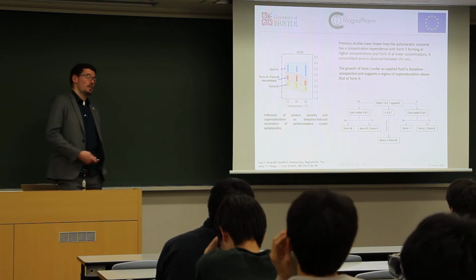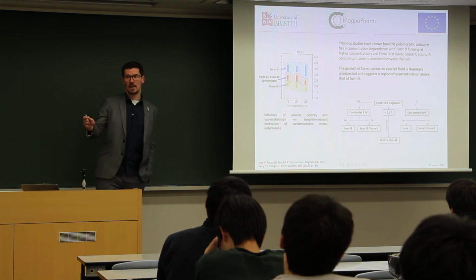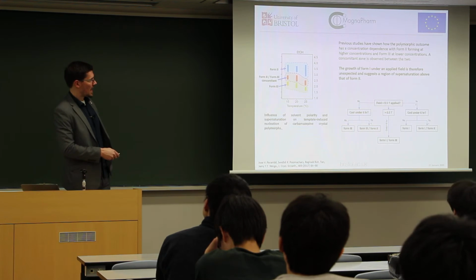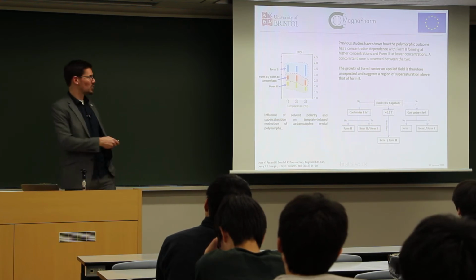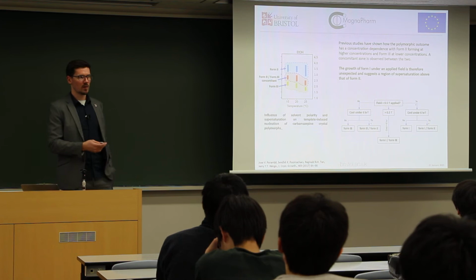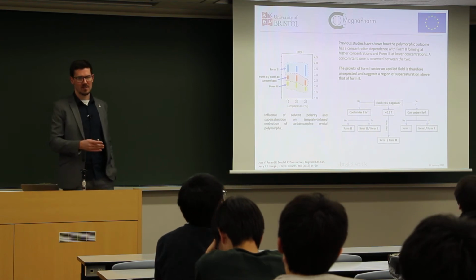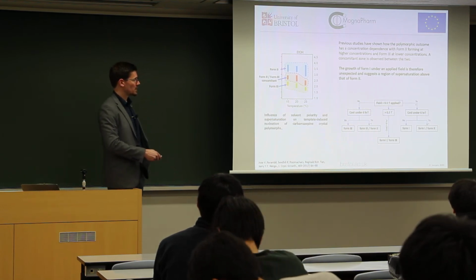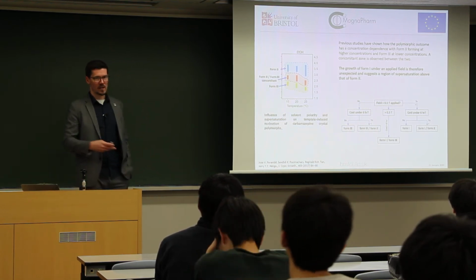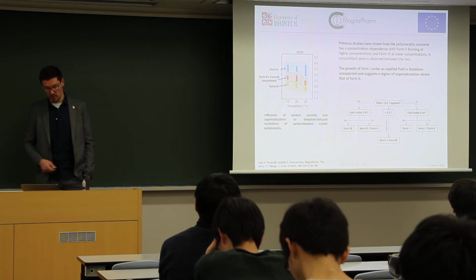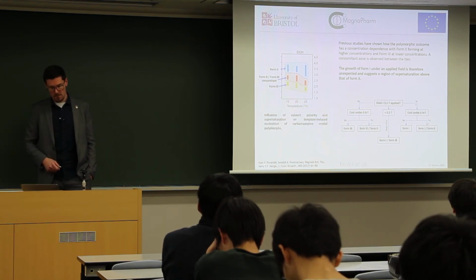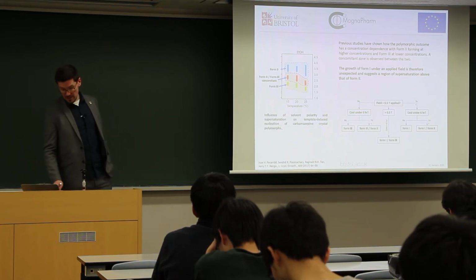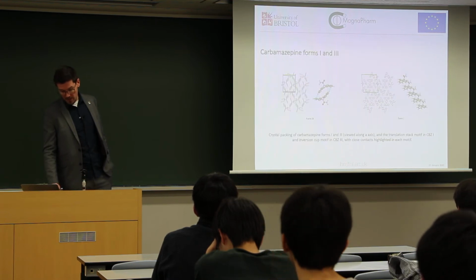So it looks like what we may have been doing is getting the suppression of crystallization into that little wedge again, and increasing the supersaturation beyond which they can do with just solvent-mediated means. We're suppressing the crystallization, increasing the supersaturation, and making form 1. This is just a flow chart of how we've been getting the different forms of carbamazepine. This is now two systems in which we've seen it work.